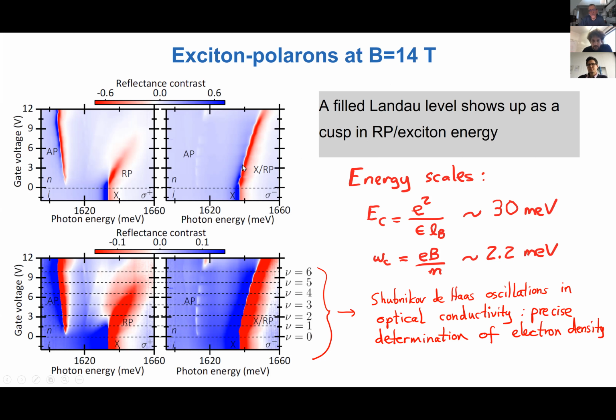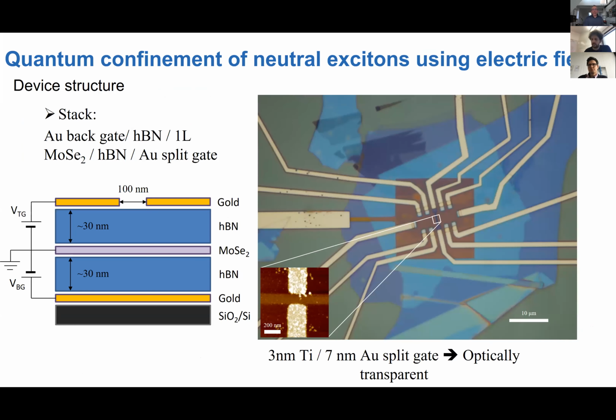So by looking at the gate voltage and also confirming the linearity of the separation of these successive Landau level fillings with the gate voltage, we can not only determine the electron density, but also make sure that we can use the gate voltage as a nice and direct probe of the electron density in the system. Okay, and here you see the different Landau levels, and we call this Shubnikov-de Haas oscillations in optical conductivity, in analogy with the standard method that is used in low frequency transport. Okay, now that was my introduction.